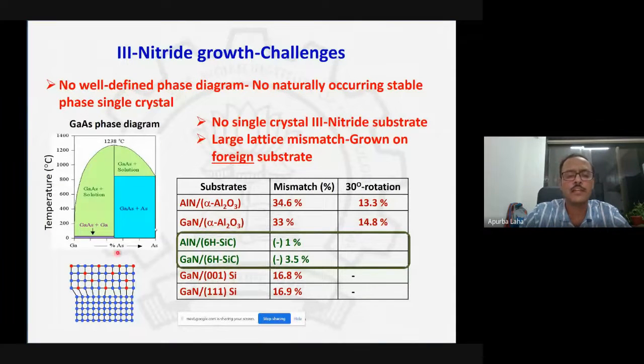If you look at this gallium arsenide phase diagram, the beauty or advantage of it is that if you look at the gallium, let's say on the left side, and the arsenic, both have a melting temperature, even though the arsenic sublimes somewhere at 800 centigrade. So if you mix them together, you have a solid that has a melting temperature of